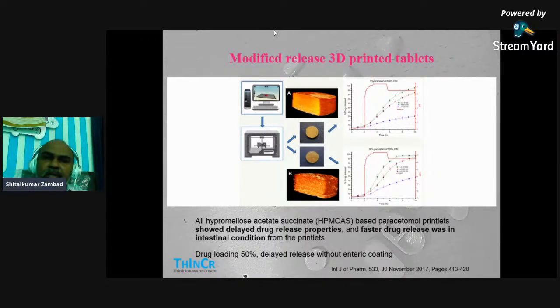after making the tablets by 3D printing, they have studied the release profile, and these paracetamol printlets show delayed drug release properties, and faster drug release was observed in the intestinal condition. So here there is a possibility of delayed release without enteric coating. So without enteric coating, there is a delayed release of the paracetamol.